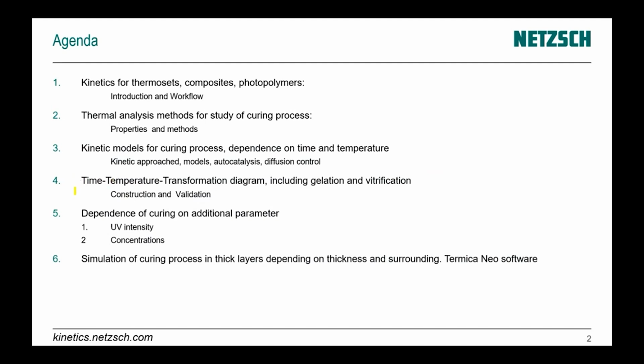And then we have a very new part of our Kinetics Neo software: dependence on additional parameters. The first part is dependence of UV curing on UV intensity. Here we will be able to create a common kinetic model, which depends not only on temperature, but on UV intensity as well. The next part of this section is the dependence of the curing on the concentration ratio of the reactants. Here again, we will create a common kinetic model, which depends not only on temperature, but additionally on the concentration ratio of reactants. And the last part is the simulation of the curing process in Thermica Neo software.